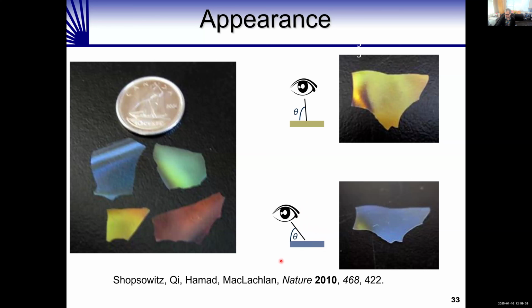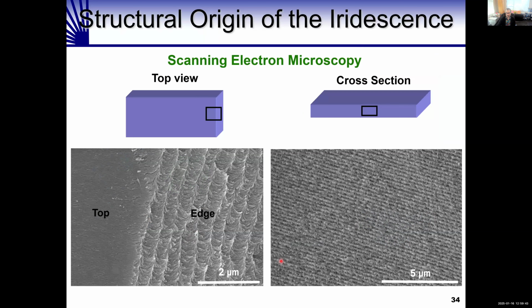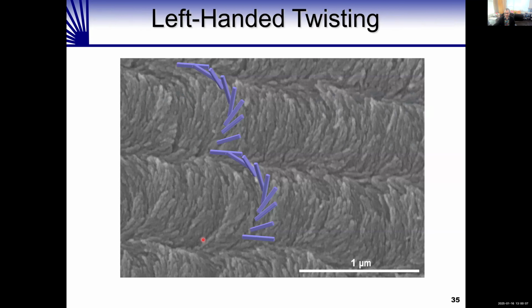To study these materials, we look at them by a lot of electron microscopy, in particular scanning electron microscopy. If you take a film, cut it, and look at the cross section, you can see a pretty well-ordered layered structure. The top of the film is relatively smooth, and the edges have these undulating features. We've looked at these by high-resolution electron microscopy, and you can actually resolve a left-handed helical twist to the silica. Remember, there's no cellulose here—this is the pure silica film we're looking at, and we can see that the helical structure of the cellulose nanocrystals has been transferred to the glass through this templating effect.